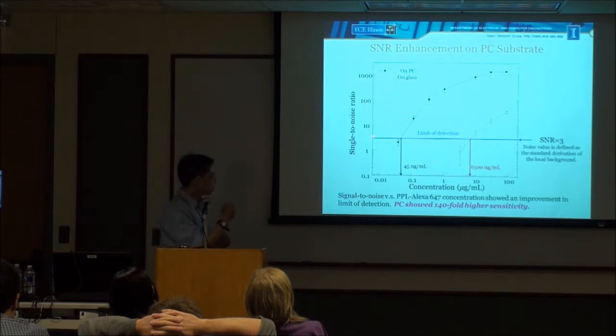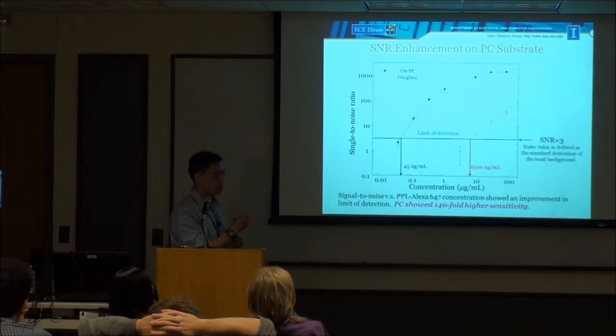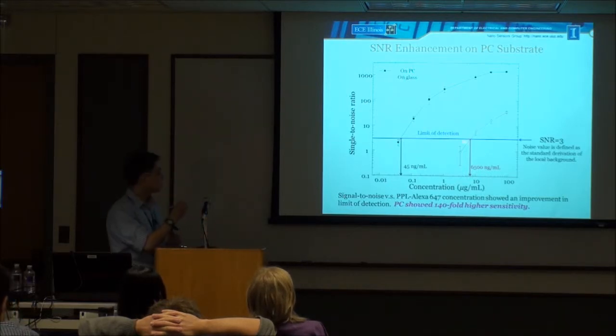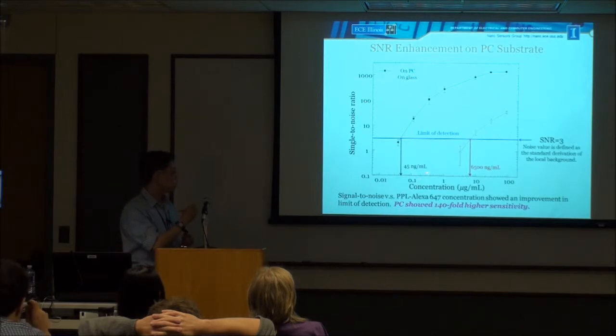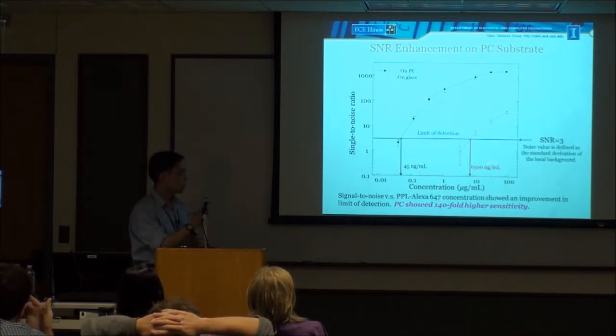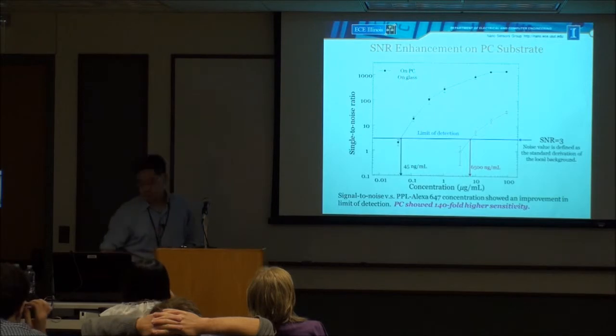And if you look at the limit of detection, on glass substrate you can only see a very high concentration, which is 6.5 microgram per mL. In comparison, the photonic crystal sensor is able to see 45 nanogram per mL, which is 140-fold lower than the concentration that you can see on glass substrate.